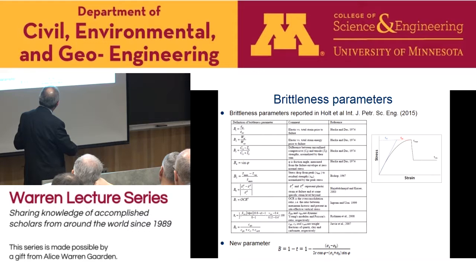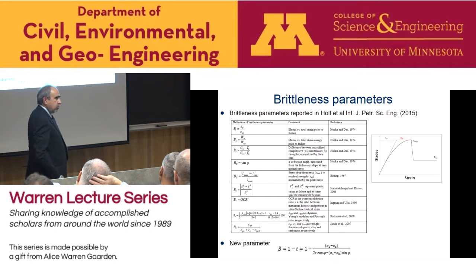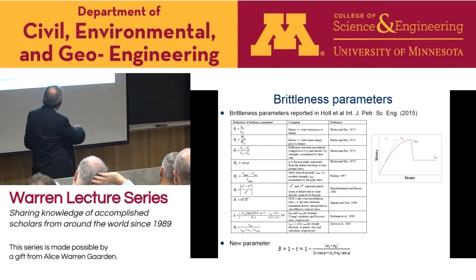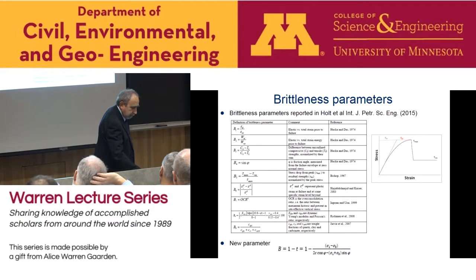This was one of the formulas proposed, which has some problems because this formula doesn't predict that the brittleness should decrease with confining stress. We expect that confining stress will decrease the brittleness and increase ductility. This doesn't follow the right tendency. And from the work I presented, it's clear to me that brittleness cannot be used in isolation of material parameters. It's a combination also with the confining stress. We know very well that confining stress increases the ductility. So an index should be a combination of the stress regime and the material parameters.